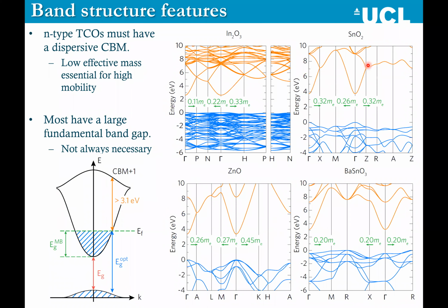So typically, when we look at the band structure of these solids, a band structure is effectively the MO diagram for a solid, just in 3 different dimensions. Normally, these materials have very dispersive conduction bands, and here we have the band structures of indium oxide, tin dioxide, zinc oxide, and barium stannate. You can see that we have in orange the conduction bands, the unoccupied states, and in blue the occupied valence band states. The conduction bands are very, very curvy.